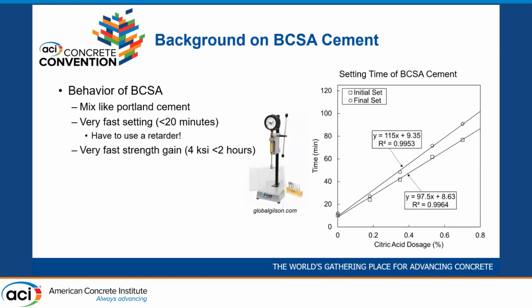As far as setting time goes, the set retarder that we've used mostly at the University of Arkansas is citric acid, which is a food grade citric acid. And we did some setting time tests with the mortar penetrometer. And we found that if you don't use any citric acid, the cement sets up in just over 10 minutes, but that the setting time can be increased linearly with increasing citric acid dosage. And if you look in the middle of this figure, around a 0.35% dosage of citric acid by cement weight is usually what we use. And that's good for about 45 minutes of working time. But we haven't found too many negative effects with adding additional citric acid after that.